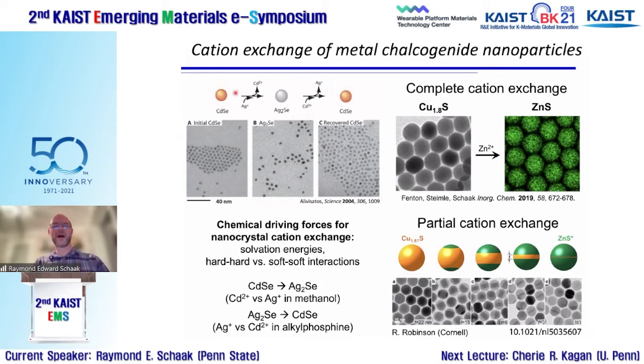But from a very high level, this concept and these techniques let you take something like a cadmium selenide quantum dot and kick out the cadmium while replacing it with silver that was initially in solution. So the silver from solution comes into the particle, the cadmium that was in the particle goes into solution. And in the process, the anions stay relatively fixed. We know a lot more about that in the past few years, but you can consider on time scales, the anion sublattice is staying pretty rigid, and the cations are shuttling in and out at a much faster rate.